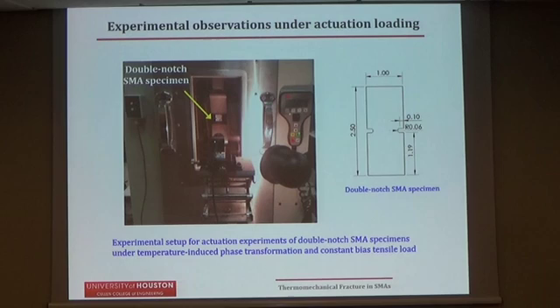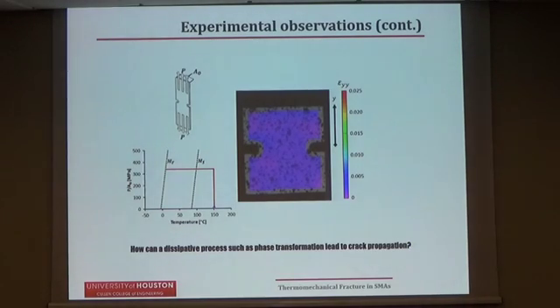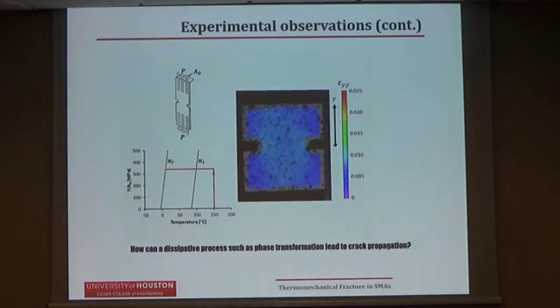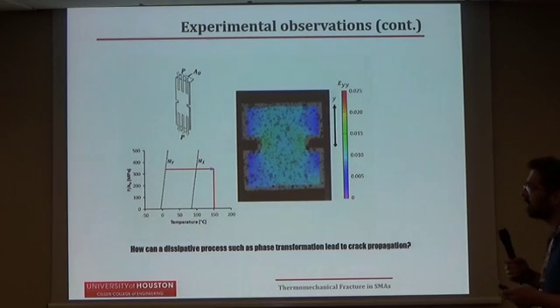So once more, we apply a mechanical load at a high temperature. This load, for the experiment that I'm going to show you, is just 50% of the load needed for failure at that temperature. And then we cool down and the material fails. So the question is, why does it fail?